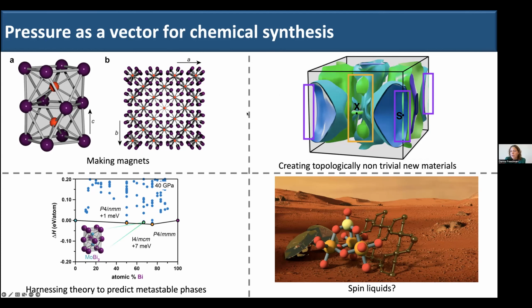Yeah, so there are two parts to that question. The first is, do they persist outside of the pressures that you access them at? And the second is, do they persist down to ambient pressure? We found that everything that we've accessed at higher pressure persists down to pressures where they're not thermodynamically stable anymore. About half of them persist down to ambient conditions. Understanding what changes are occurring in the bonding, and to what extent we can count on kinetic stabilization, which is what you're doing when you're releasing the pressure, is one of the things we're most interested in. Thinking about how the bonds are changing when you release the pressure, that's the interesting part, right?